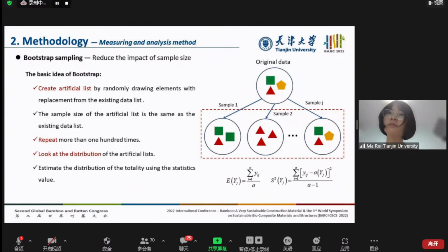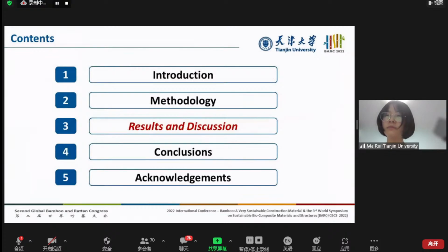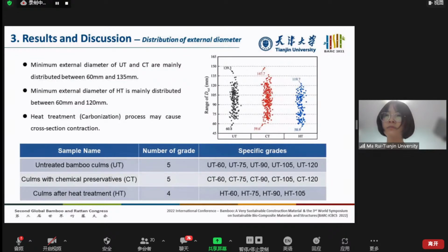To reduce the impact of sample size, the bootstrap method is adopted for statistical analysis of dimensional parameters of different grades of bamboo. Let's see the results. As can be seen in this figure, the minimum external diameter of UT and CT is mainly distributed between 60 millimeters and 135 millimeters, while the value of HT is mainly distributed between 60 millimeters and 120 millimeters. Thus, it is strongly recommended that UT, CT, and HT could be divided into 5, 5, and 4 groups respectively.